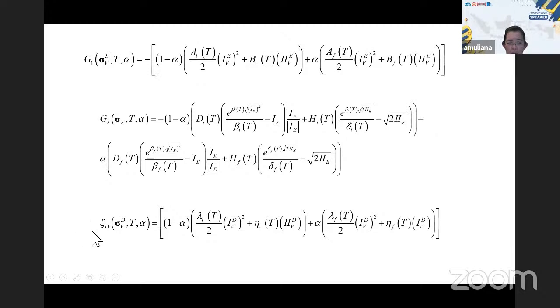The other one is what we call dissipation due to the delayed response. We also have a material parameter here, which is also temperature dependent. This material parameter is associated with the viscosity of the material. That is where we get the viscoelastic response of this material, while we are also looking at the microstructural changes. When you look at this, I have this alpha, the parameter that I mentioned earlier, right? This is what we have as the volume fraction of the new microstructure.